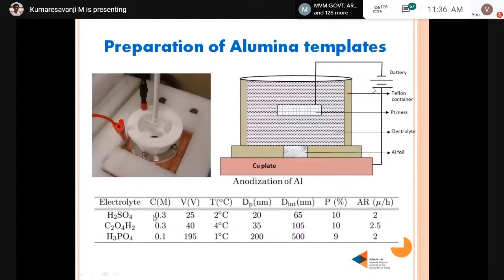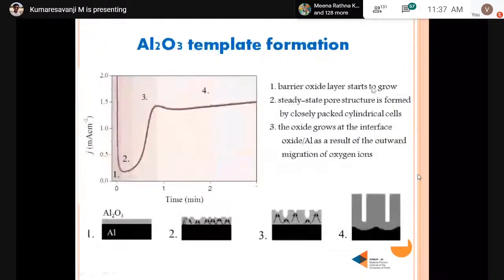Depending on the different electrolytes, if you do the anodization, you can get different pore sizes. For example, with sulfuric acid you will get 20 nanometers, with oxalic acid you will get a nanopore diameter of 35 nanometers, and with phosphoric acid you will get about 180 to 200 nanometers. And also with the different electrolytes, we have to deal with different potentials and different temperatures. So this is how it is going.